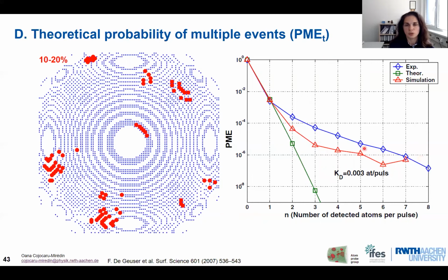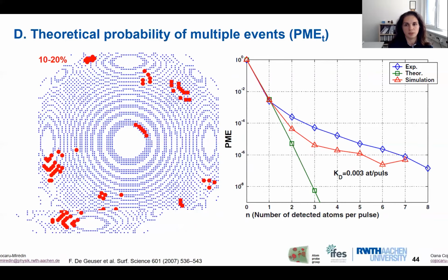And this had been shown also by doing simulations that we end up having a very high fraction of probability of multiple events, much higher than had been proposed theoretically. So actually these two results show that the evaporation at the tip surface does not really follow a random statistical behavior. The atoms are sitting within the terraces. We have positions which have a higher field, so we have a higher probability of getting field evaporated than other positions. And this is why the field evaporation process is a pretty complex behavior.